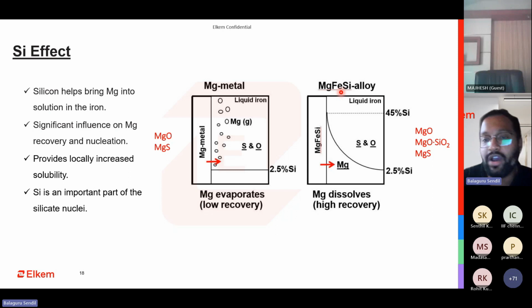That is why if you see cored wire, they use pure magnesium. At the same time, they have some amount of ferrosilicon magnesium also in it, because you need to have the magnesium coming into the liquid metal at the correct time, at the correct rate, so that you take the maximum benefit out of it. Otherwise, you are just mechanically forcing something to happen. Out of 100% you add, the recovery will be 30 or 40%. But if you are able to balance the timing in which it comes out, your recovery can go up to 80, 90%. If the recovery goes high, you save a lot of money. Your addition percentage will come down. So this is the impact of silicon, and also the impact of reaction violence.